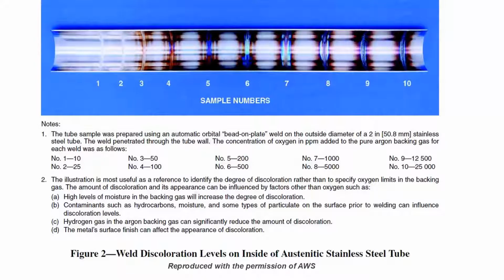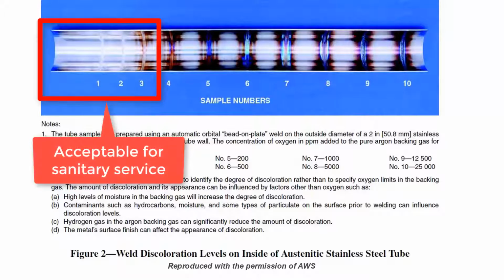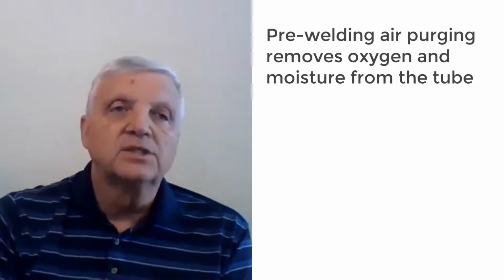which displays a range of weld discoloration that results from various amounts of oxygen contamination. For sanitary service, a discoloration level of 3, produced by only 50 ppm oxygen or lower, is considered acceptable. In order to achieve this low level of discoloration, the purity of the gas is essential.